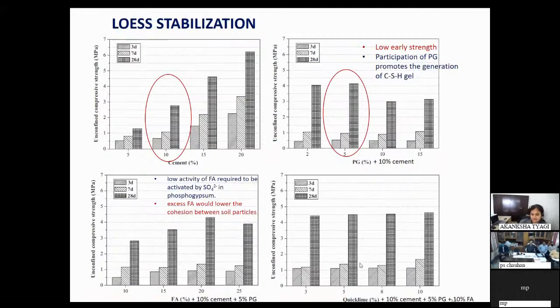And then this group of researchers also added quicklime to the 10% cement, 5% phosphor gypsum, and 10% fly ash. And if you look at these results, there is not much change, and you will see that the strength is almost equal.